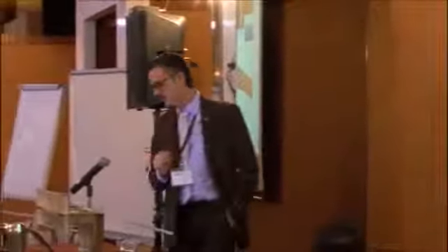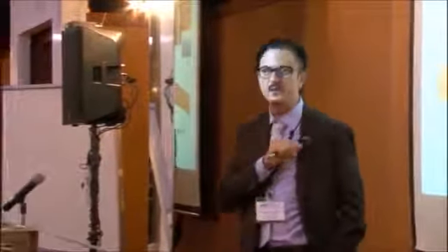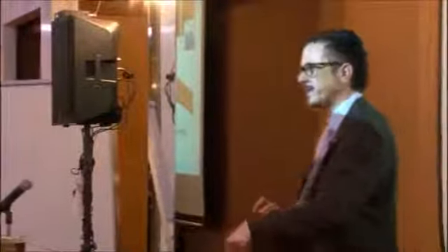So, this is done conventionally with glued-in rods. I showed you the front page. There, in this structure, in the parasol in Seville, I guess 2 million glued-in rods were used. And for those who are not familiar with this system, glued-in rods means you have a high tensile strength like a screw. You drill a hole into the timber, and this hole is, according to the design code, 2 millimeters larger than the rod itself. Then you use a special glue. It's an epoxy or